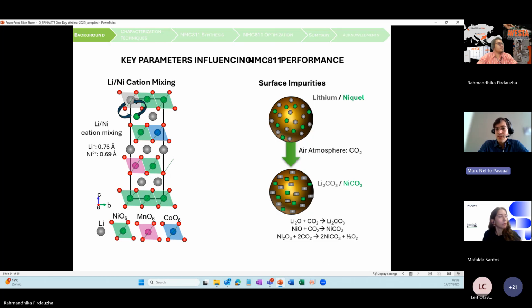The surface impurities are usually formed by lithium and nickel, which are the most reactive elements in the surface of this NMC 811, because they are also the most abundant ones. And they react with carbon dioxide from the atmosphere or even water vapor to form carbonates or hydroxides. The same goes for these kind of impurities. You are reducing the amount of lithium and nickel active in your material, so you are reducing the capacity, and at the same time they act as resistive elements.